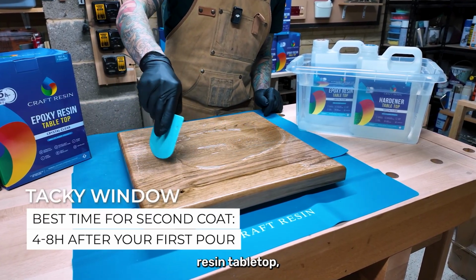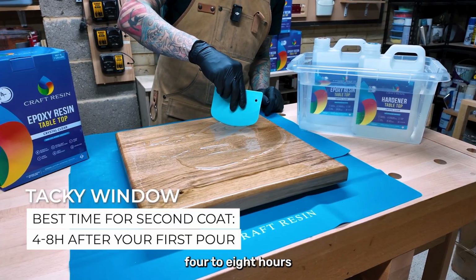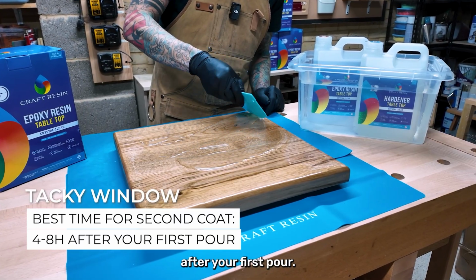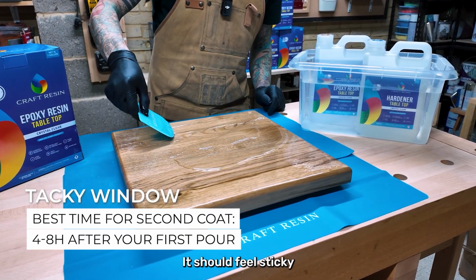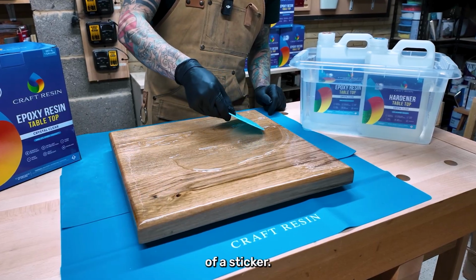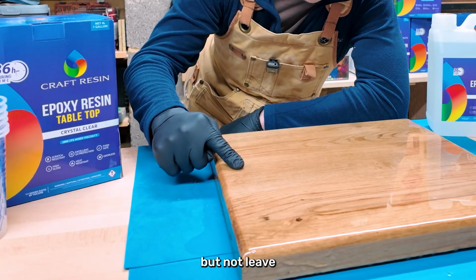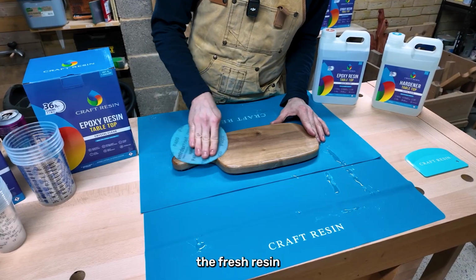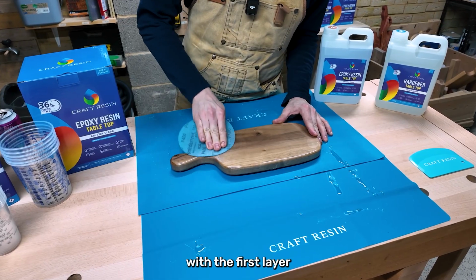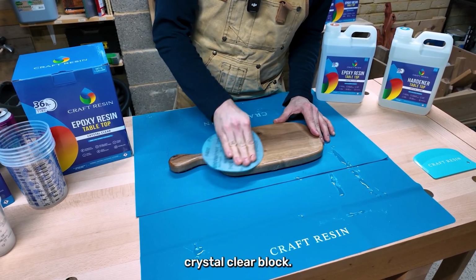With Craft Resin Tabletop, this usually happens 4 to 8 hours after your first pour. Tap the surface with a gloved finger. It should feel sticky like the back of a sticker. It should grab your glove but not leave a fingerprint. At this stage, the fresh resin chemically fuses with the first layer to create one solid crystal clear block.